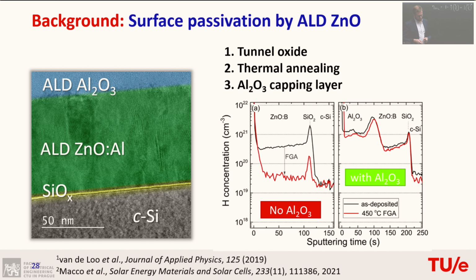So what was done here was again to use this already well-known aluminum oxide process and stick it on top of our zinc oxide. And then we see in this SIMS picture over here that if you do forming gas annealing, this FGA over here, if you have no aluminum oxide capping layer, you lose a lot of hydrogen. If you put a capping layer on top, before and after annealing, it's kind of the same. So this really shows that the hydrogen is preserved in your zinc oxide.